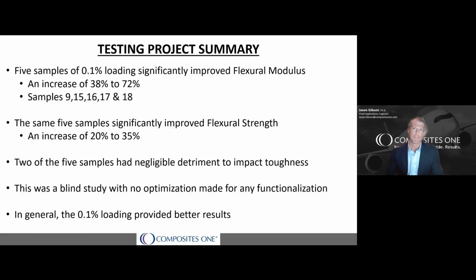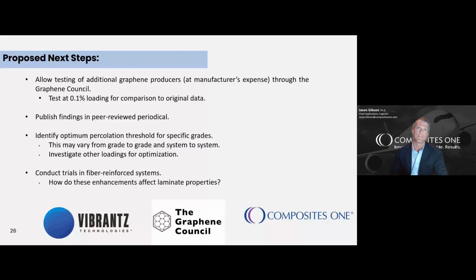So in quick summary, we have 5 samples at 0.1% loading that showed significant improvement in flexural modulus and strength. Out of those 5 samples, 2 had negligible impact on the toughness of the resin. Now, I want to reinforce that this was a blind study, so there was no bias given to any graphene supplier. However, that also means that we could not optimize for any type of functionalization the suppliers may have done. And as we mentioned, in general, the 0.1% loading provided the better results.